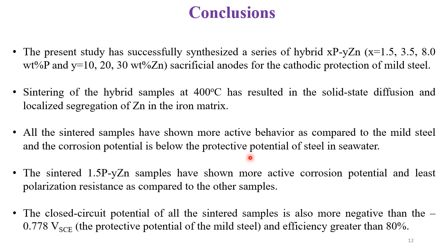So we can say here that the present anodes which we have developed, that is the HPPI zinc based hybrid anodes, have the potential to be used as a sacrificial anode and can be used as an alternative to the zinc based anode, as they show much comparable anodic performance parameters. Along with that, they are much more cost effective as compared to their counterparts.